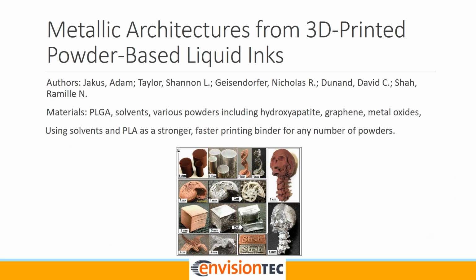All right, and the final example, and this is very exciting because it represents a non-medical purpose or application, rather, of the bioplotter, and that is creating metallic architectures from 3D printed powder-based liquid inks, which is simply another version of the 3D printed metal and ceramic construct I mentioned earlier. This is a much faster method with higher loading than using a viscous binder, again, that polyvinyl alcohol and methyl cellulose. In this case, Shaw Lab from Northwestern used a little bit of PLA powder, some solvents, and then the particle of interest, and they were able to create highly loaded ceramic and then subsequently metal scaffolds by sintering these objects together. And here it better illustrates the process.